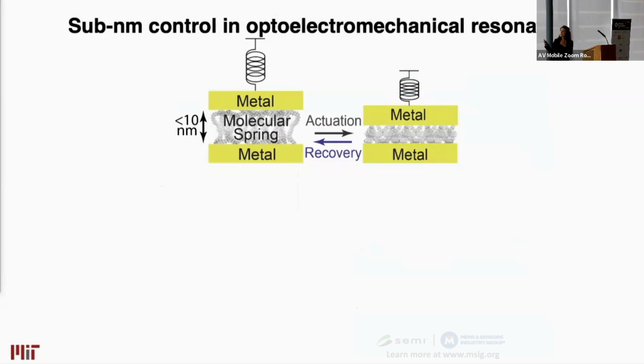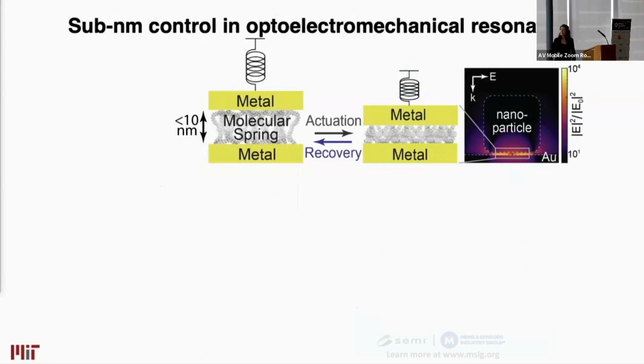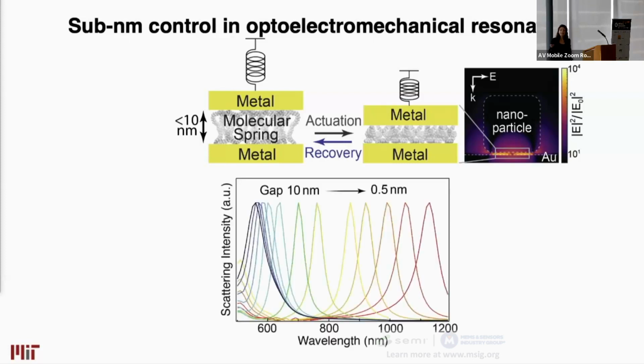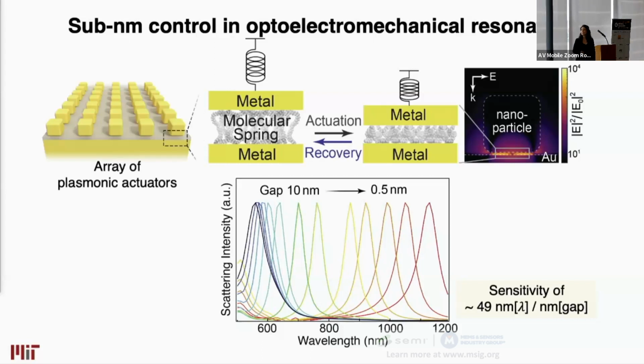Just to give you a brief overview, we've used it to create optoelectromechanical resonators in the form of nanoparticle-on-mirror plasmonic structures, where the optical response of the structure is heavily dependent on the structure and geometry of the gap in your plasmonic resonator. You can see that we can get as much as 50 nanometers of spectral change in the spectral response of these optical structures as a function of just a nanometer change in the switching gap.